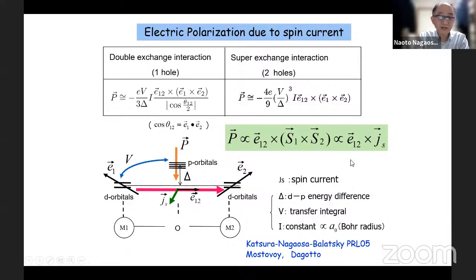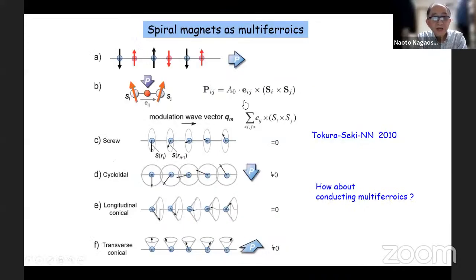So people call it a spin current mechanism of spin-induced electric polarization. So based on this formula, you can predict the relationship between the spin structure and the polarization. So in this proper screw structure, you don't have any polarization according to this formula. But in the cycloidal case, your polarization is in this direction, but in the longitudinal conical, you don't have any polarization. But in the transverse conical, you have this direction of the polarization. So the spin structure and this polarization have almost a one-to-one correspondence according to this very simple formula.